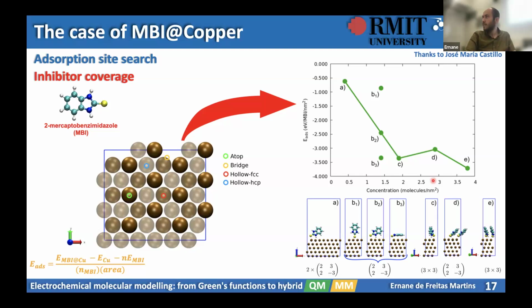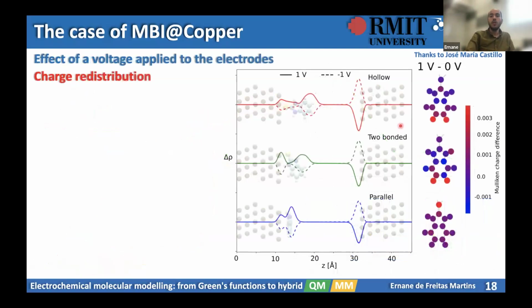Then what happens, because this is just DFT, no voltage, no water? What happens if we apply voltage here? For these 3 adsorption cases, 3 examples, here we see the difference between the case at 1 volt and 0 volts, and at -1 volt, for 3 different adsorption sites. We see that because of the voltage, there is charge accumulation at the molecule's tail here.